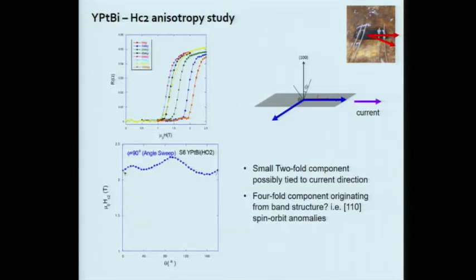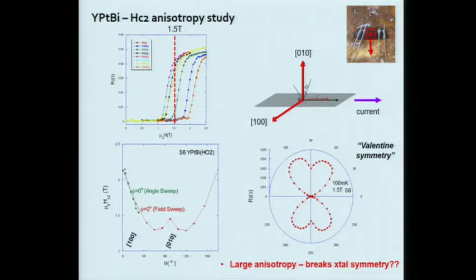And you can see there's some wiggle here. This is the HC2, as determined by resistive transitions. You can see that there's both a twofold and a fourfold oscillation here. And we think perhaps the twofold could be coming from some displacement due to the current direction, and then the fourfold part is just the crystal symmetry. Good enough. That's not so bad. But what was more interesting was when we stayed transverse to current and just rotated from, let's say, this principal axis to this one, which are identical, right? Crystal symmetry. And we see this very strong anisotropy. So this goes from parallel to the plane direction to perpendicular, and it changes by almost 50%. And then there's some small other oscillation here.